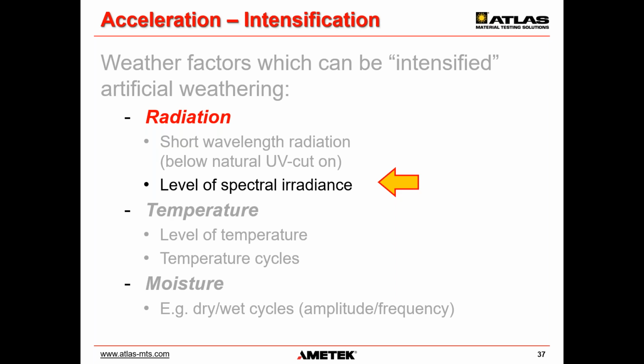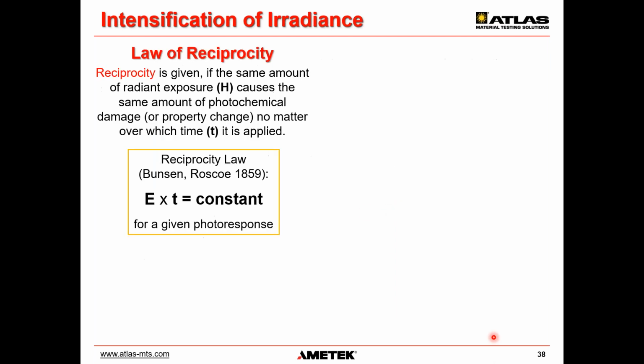But running tests at both increased irradiance and increased temperature, however, is quite uncommon. The reason being that it generally leads to poor correlation as we start to throw the natural balance of the stress factors out of normal. So with irradiance intensification, we now need to talk a little bit more about the law of reciprocity, but I don't really like law. Law is too absolute. I like better principle or concept.